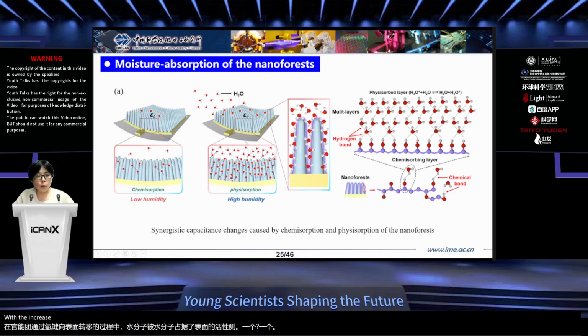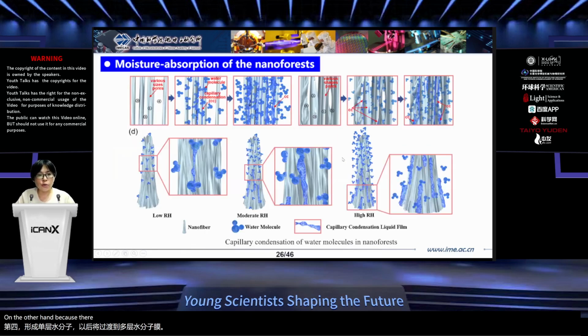With the increase of relative humidity, physical adsorption can occur under the action of van der Waals force, forming a single layer of water molecules, and later will transition to a multi-layer water molecular film. On the other hand, because there are a large number of capillary pores with different sizes and shapes in the nanostructures and in between, according to Kelvin's theory, such structure will undergo capillary condensation under different humidity conditions. Smaller pores can undergo capillary condensation at a lower humidity, and as the relative humidity increases, capillary condensation also occurs